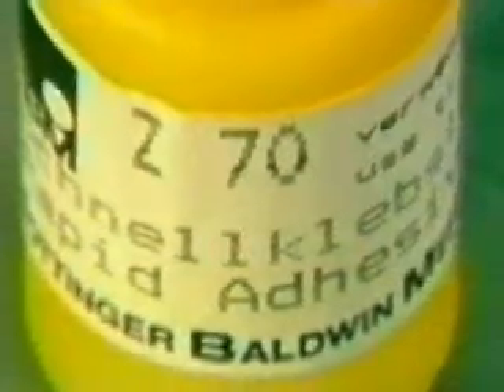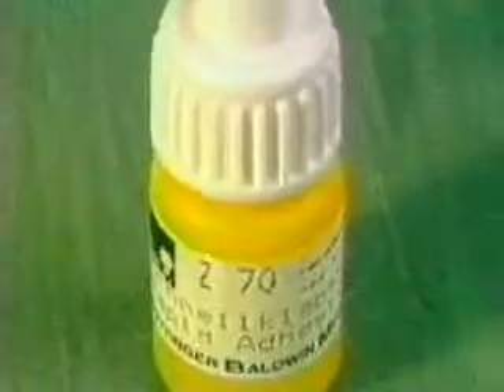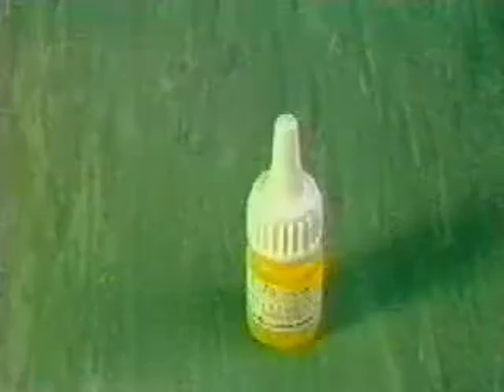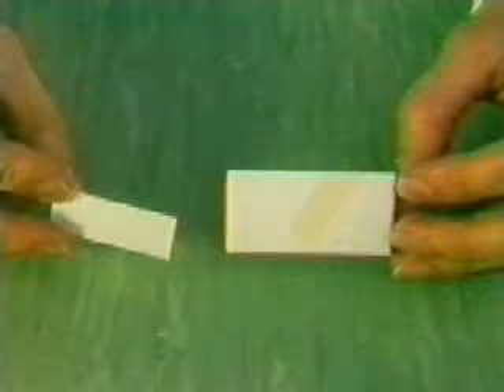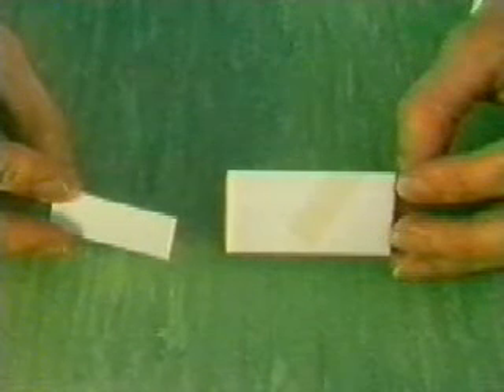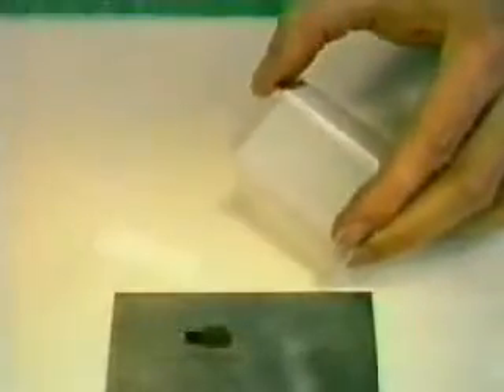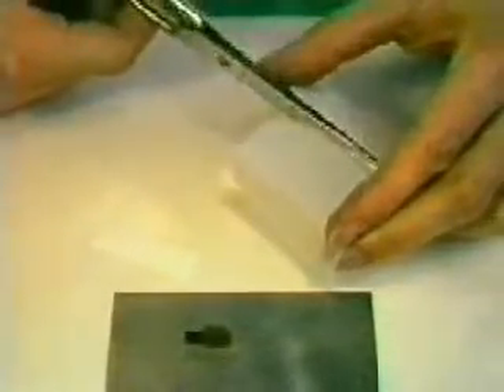The strain gauge is bonded with the Z70 adhesive. This is a 1-part cement in the cyanoacrylate group. Teflon film and Teflon strips are needed as aids in mounting. Please note that they must be free of fingerprints and other forms of contamination, at least at those points which come into contact with the adhesive, strain gauge, or test object. If necessary, clean them with solvent. All mounting aids must be ready to hand before the strain gauge adhesive is applied. The brief hardening period does not allow any spare time.